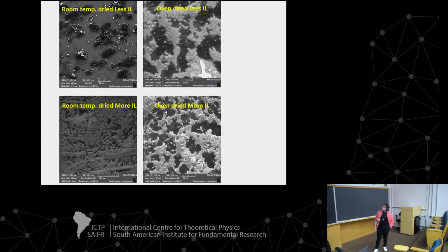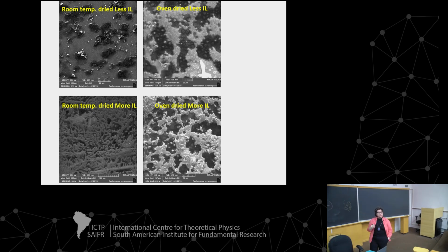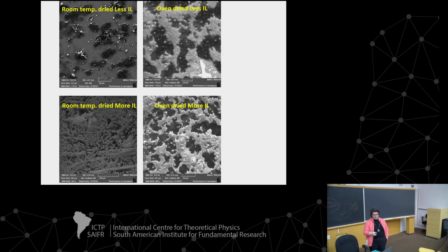What's the problem? When we dry in different conditions, we have different morphologies of the materials. We have two materials, with more ionic liquid and less ionic liquid, and we tried drying them by self-assembly at room temperature and in an oven, with more concentration and also at room temperature and oven dried. But in all these conditions, the morphology was completely different, and this completely different morphology affects how sensitive the SERS sensor is. And we don't know why.